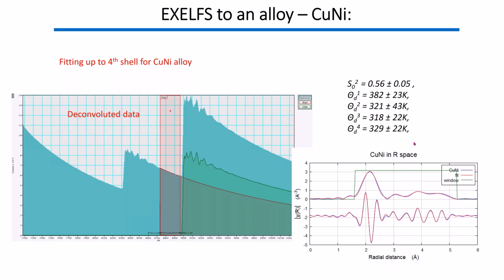We did have some plans, but you have to balance, I guess. The main reason we don't use 300 kV is the damage. At 300 kV the damage is very fast. So now we mostly choose 200 kV. Another reason for not trying lower kV like 80 or 60 yet is the energy range. At 80 kV, the largest dispersion is smaller, so you cover less energy range.